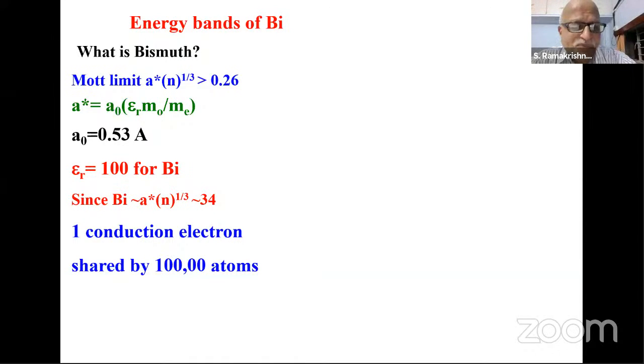So you apply it to bismuth by plugging in the values for bismuth. You see that it's of the order of 34, and so we are still safe. Bismuth can be considered as a metal. In this case, it is a semi-metal because we have both electrons and holes. But the important thing is that, unlike normal metals, where each atom shares one electron, in bismuth one conduction electron is shared by nearly 100,000 atoms. That is because its carrier concentration is only 10 to the power of 17, 5 orders of magnitude smaller.